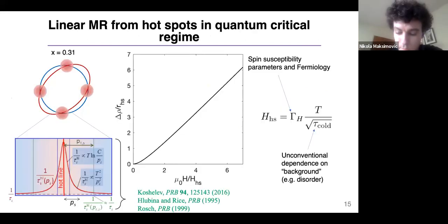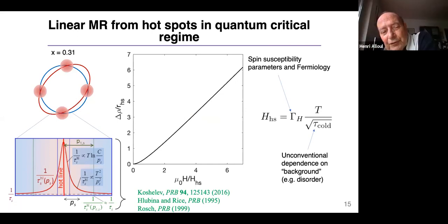So in your work, were you looking primarily at the temperature-dependent resistivity? Yeah. The thing about the magnetoresistance is that it's true you will get contributions from each band individually. But the regions that dominate the magnetoresistance are actually these quasi-particle sinks. So in our work, we've completely neglected the magnetoresistance arising from these cold regions. Okay. You primarily consider this nesting point. So you have to consider the band which has the nesting points and consider it primarily.